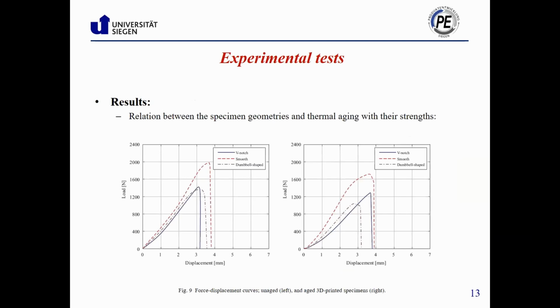In order to quantify the influence of thermal aging on the mechanical behavior of the specimens, the load deflection curves of aged and unaged specimens with different geometry were obtained, which are shown here in figure 9. Based on the obtained results, thermal aging on the specimens has led to a decrease in the failure load. The applied tensile load increases almost linearly, as you can see in the curves, according to the specimen stiffness.